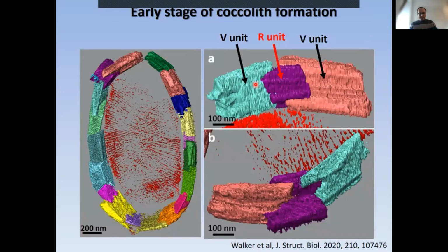And this is how the 3D reconstruction looks like. Sorry. We have here the crystals. We can see the base plate here in red. We have here some blue spherical particles at the top and some brown ones at the bottom. These are the coccolithosomes, which were calcium polysaccharide complexes that somehow survived the extraction process and remained attached to the crystals. And we have here two forming V and R units, so two different units, different crystallographic orientations.